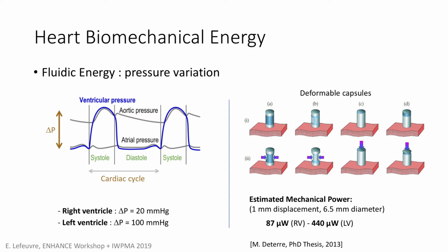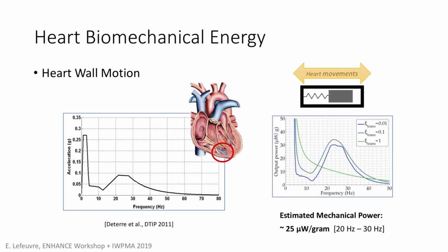So we decided to start on this kind of device or system. But before that, we also analyzed the heart wall motion, and based on numerous measurements of acceleration inside of the heart cavity, we extracted this average spectrum, and you can see here a peak at the heartbeat frequency, and we have a kind of plateau in the range of 20 to 30 hertz.